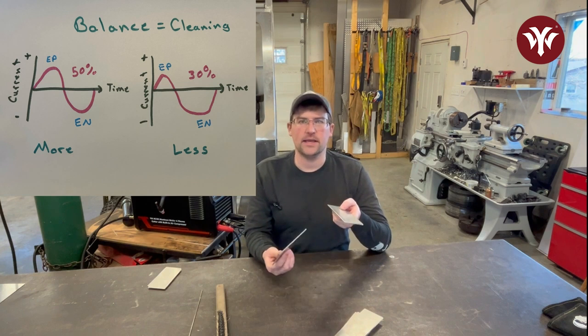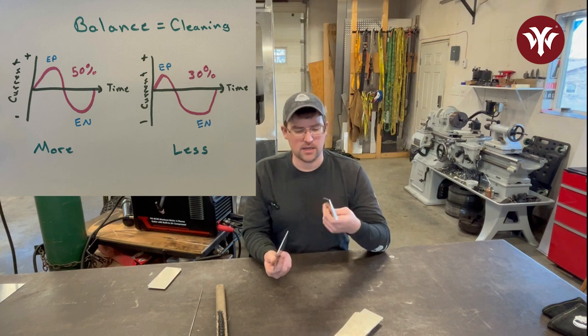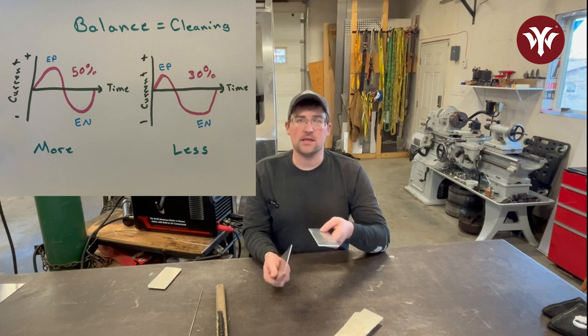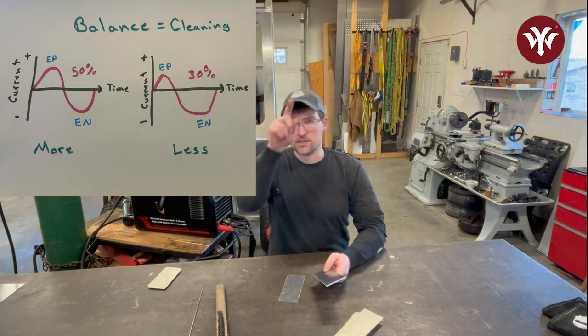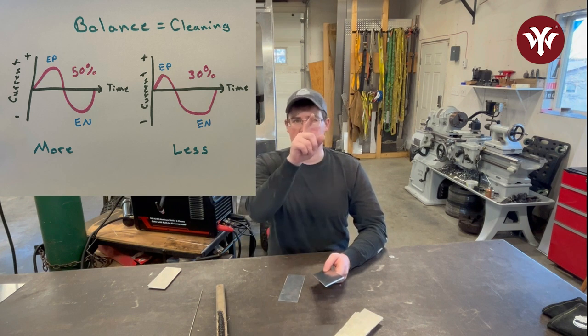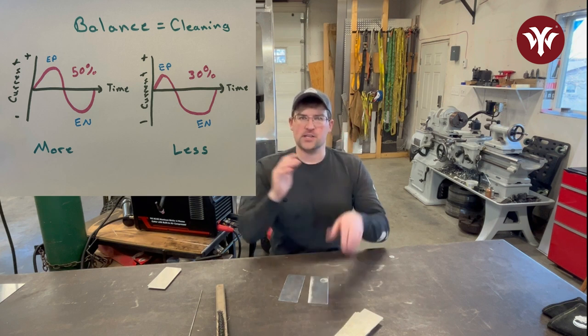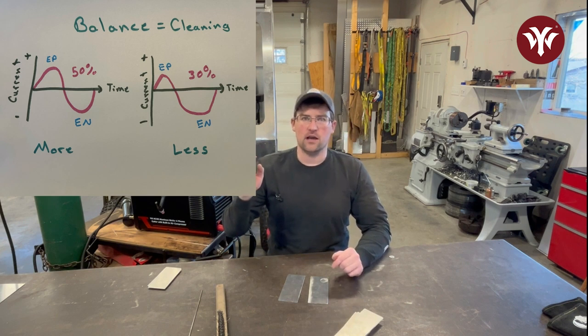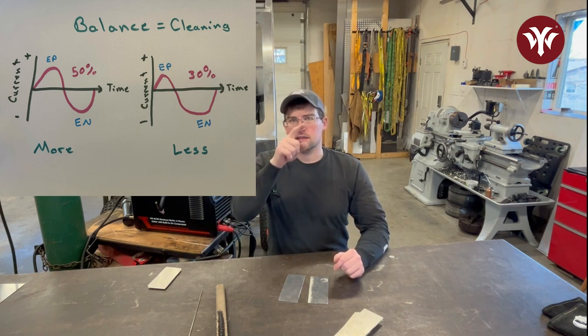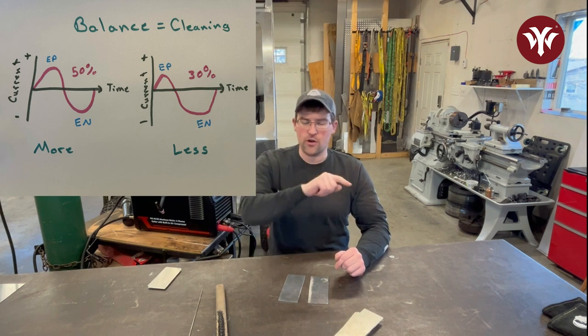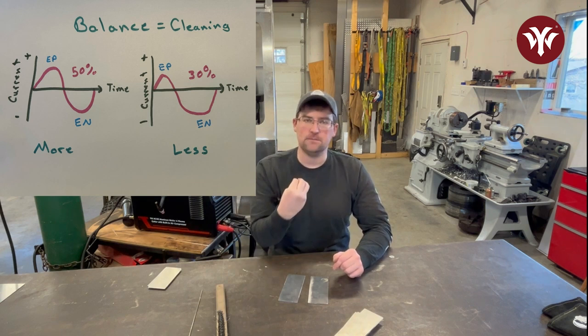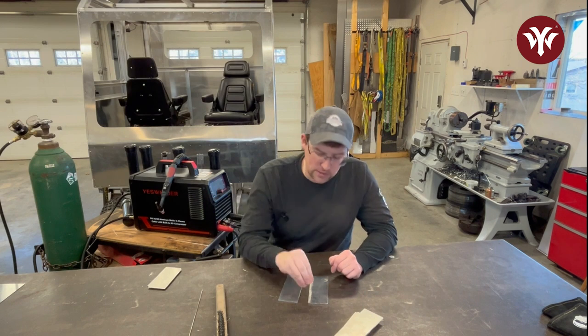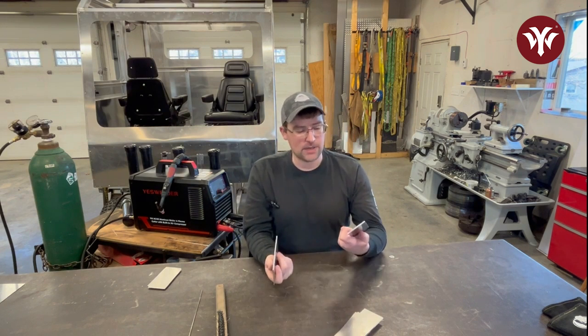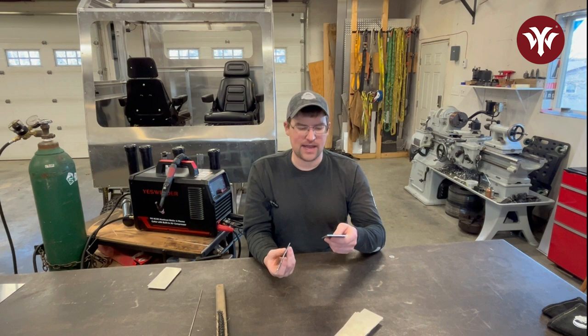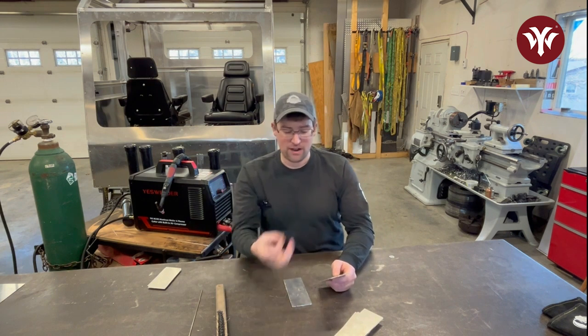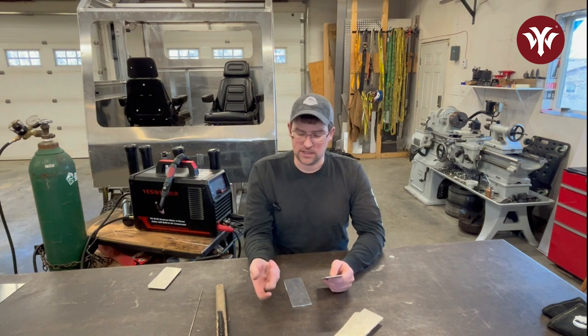With nice clean aluminum like this, we're probably going to be using a balance setting of around 30%. What that means is on your waveform, the positive or the EP, electrode positive, will be only 30% of the total waveform, leaving the other 70% EN, electrode negative. So 30% of that wave is going to be cleaning the aluminum and 70% is going to be welding the aluminum. If you got into more contaminated materials like castings or different things like that, you can adjust that balance up so you have more cleaning action and less welding.